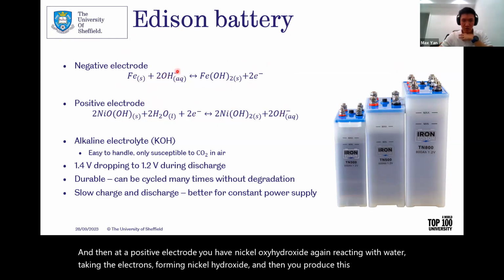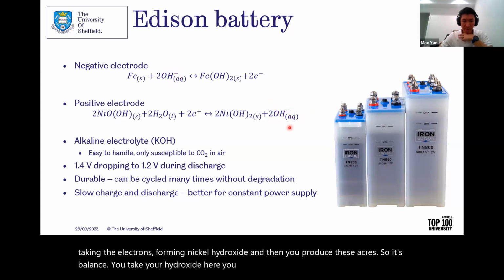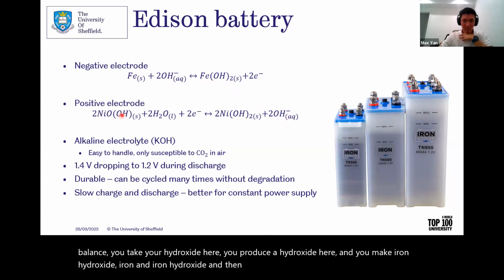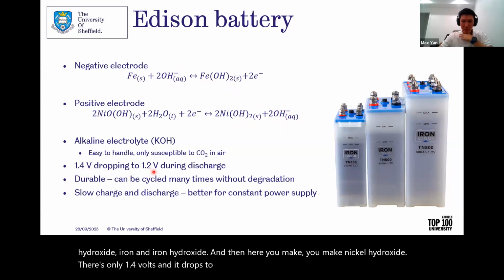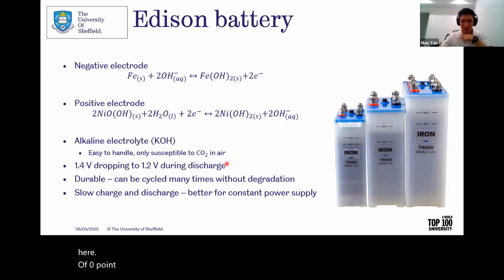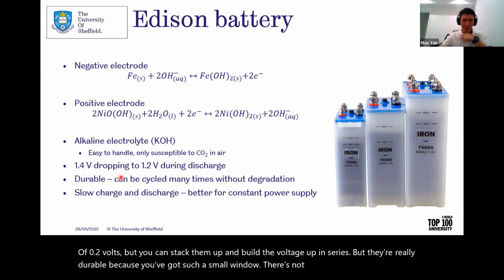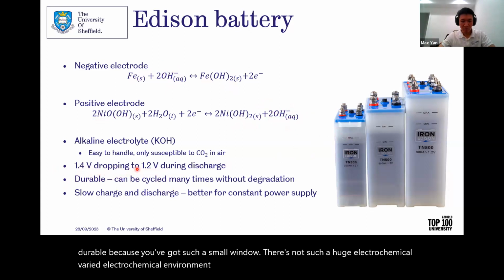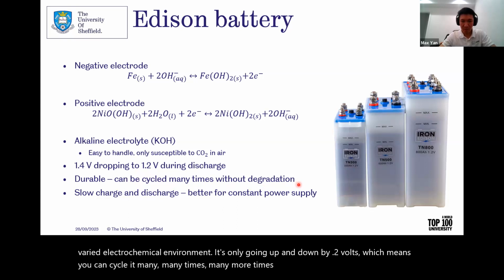So it's balanced. You take a hydroxide here, you produce a hydroxide here, and you make iron and iron hydroxide, and then here you make nickel hydroxide. It's only 1.4 volts, and it drops to 1.2 volts during discharge. So you only have a voltage here of 0.2 volts, but you can stack them up and build the voltage up in series. But they're really durable because you've got such a small window, there's not such a huge varied electrochemical environment. It's only going up and down by 0.2 volts, which means you can cycle it many, many times, many more times than 30,000 cycles or something.